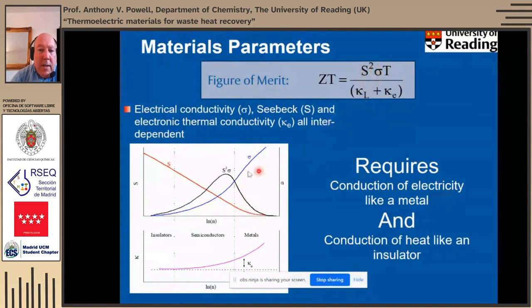So this S squared sigma term is known as the power factor, and that peaks somewhere in the middle here, which corresponds to heavily doped semiconductors. There's also the thermal conductivity element of that, which is an issue, in that whilst the lattice part of the thermal conductivity is largely independent of the carrier concentration, the electronic part will of course get higher the higher the electrical conductivity, and in fact they are directly related to each other through something called the Wiedemann-Franz law.